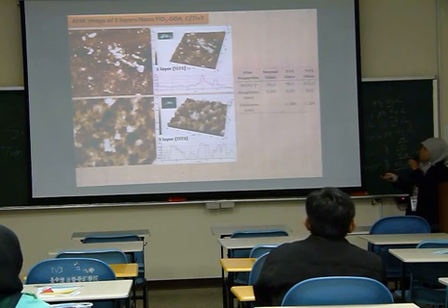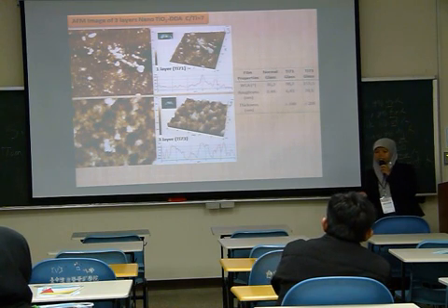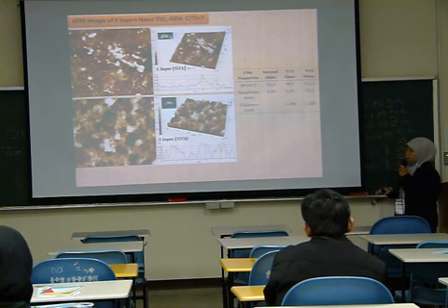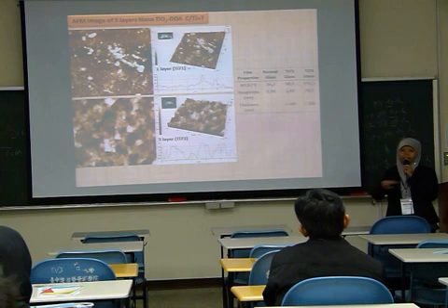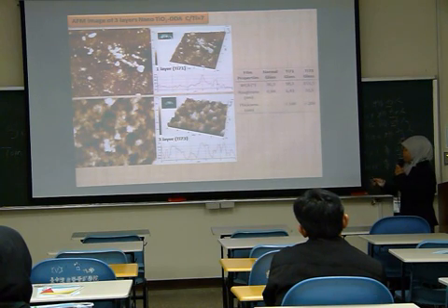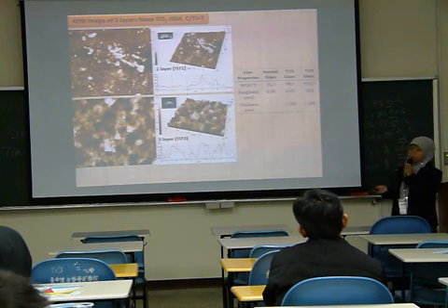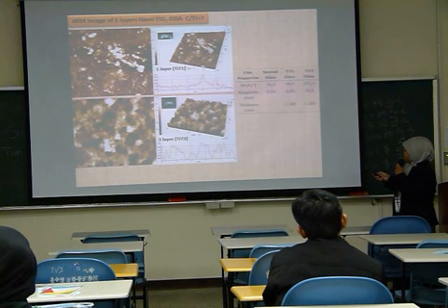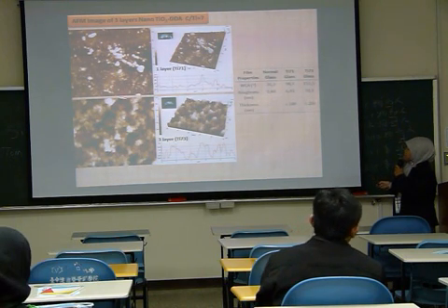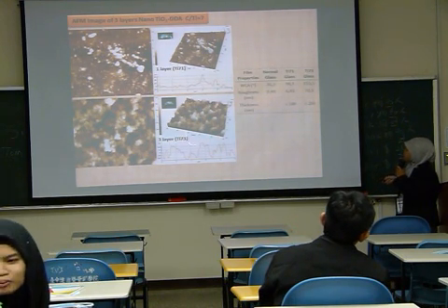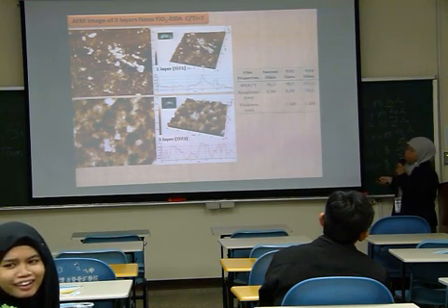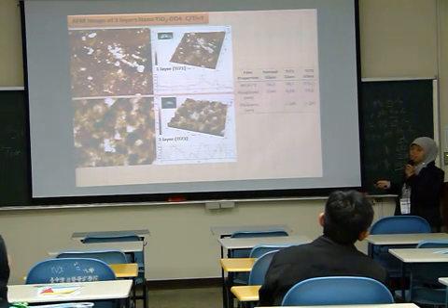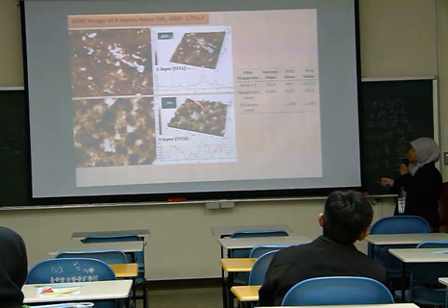You can see in this AFM image, this is the surface of the nano film. If we look at the glass manually, it is flat, but if we look through the instrument, it is very rough. So with the increase of the composition, the surface roughness is increased. It's really rough. In this micro and nanoscale roughness, we can see the hydrophobic increase in this glass.